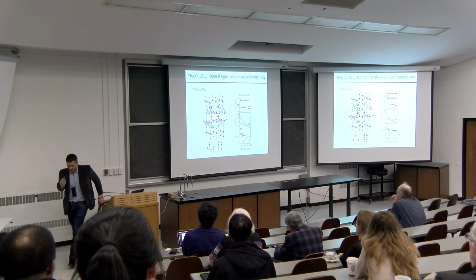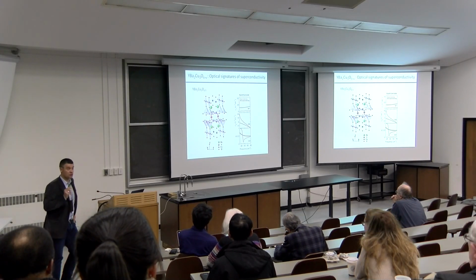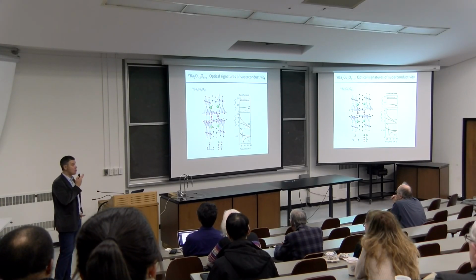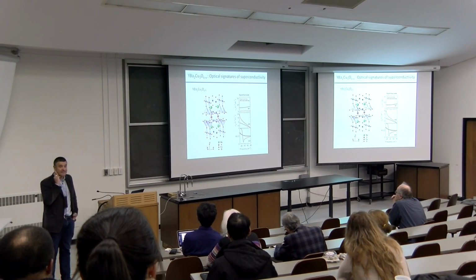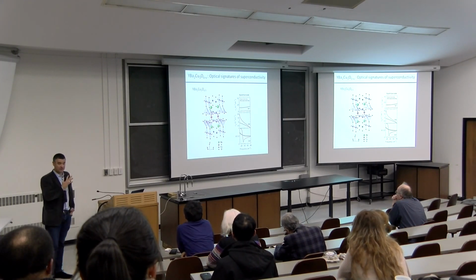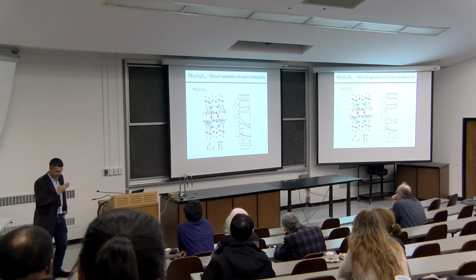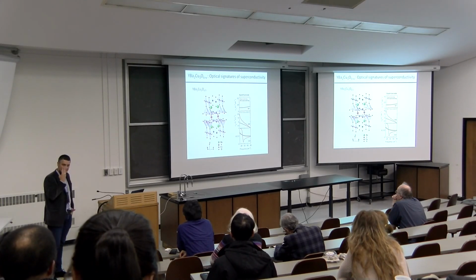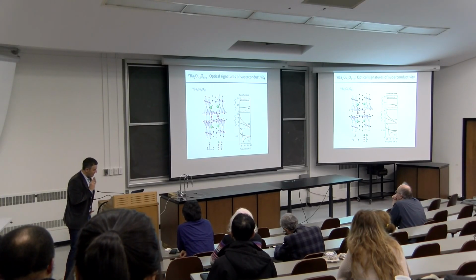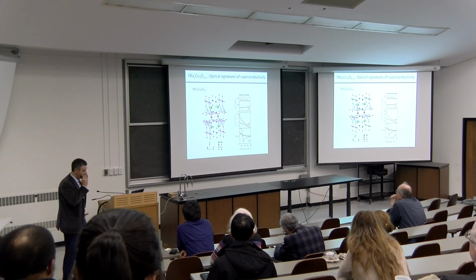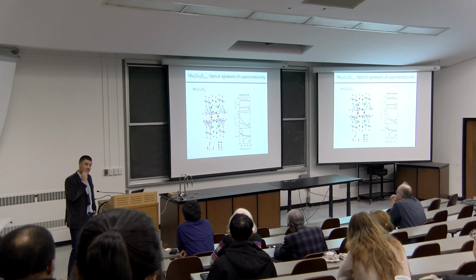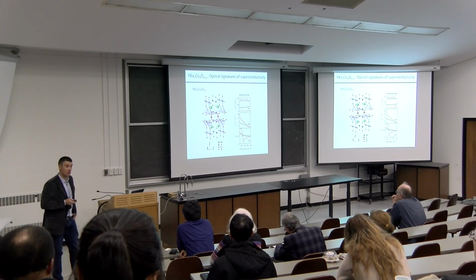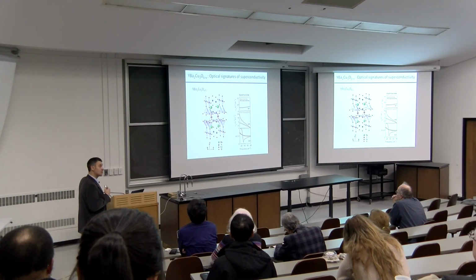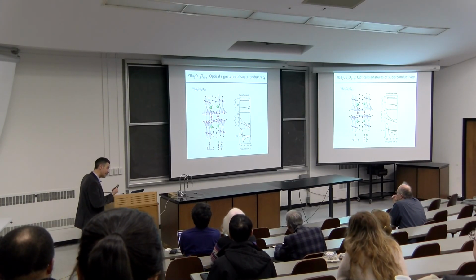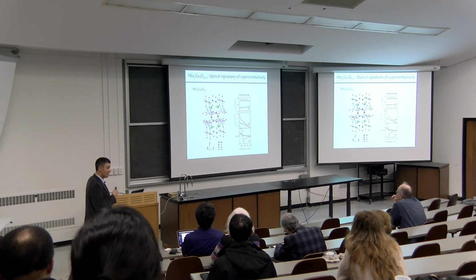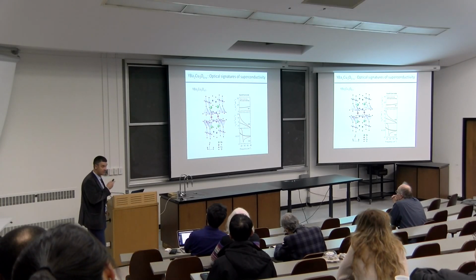Okay, so because these phenomena are going to be transient, normally the way you diagnose superconductivity is by looking at the DC properties. So superconductivity is basically a DC phenomenon. So maybe saying a transient superconductor is basically not a superconductor. But one would look at infinite conductivity at zero frequency and perfect diamagnetism at zero frequency, the so-called Meissner effect. However, there are also signatures at finite frequency in the optical spectrum that usually are considered synonymous in equilibrium with the superconducting state.